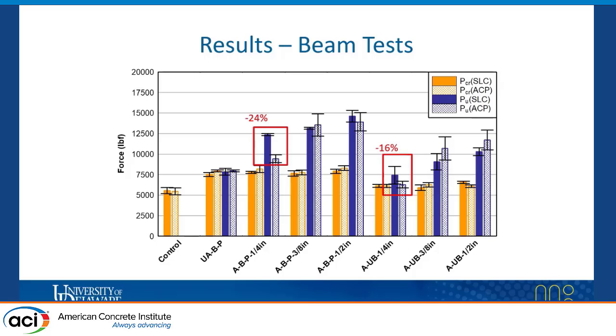And lastly, the purple hatched bars demonstrate the ultimate capacity of the ACP group. And what's important to take away here is that the quarter-inch anchors demonstrated the most susceptibility to the effects of hygrothermal conditioning. The anchored bonded quarter-inch group decreased in ultimate capacity following conditioning, amounting to 24%, whereas the anchored unbonded quarter-inch group decreased by 16% in ultimate capacity.